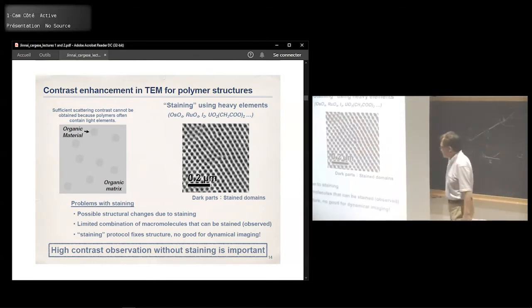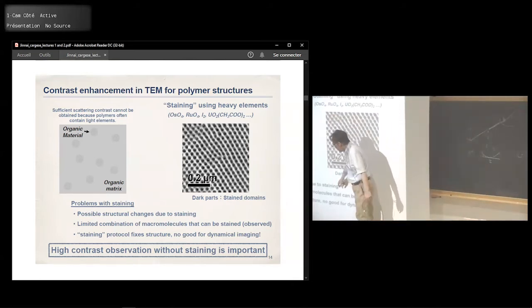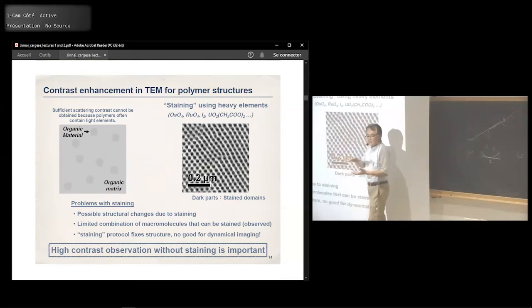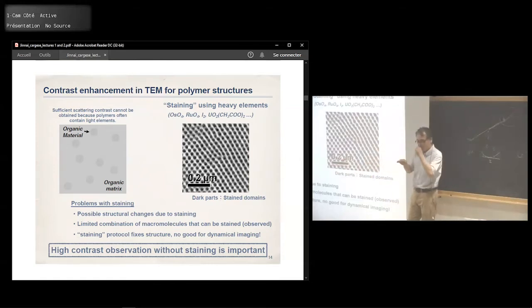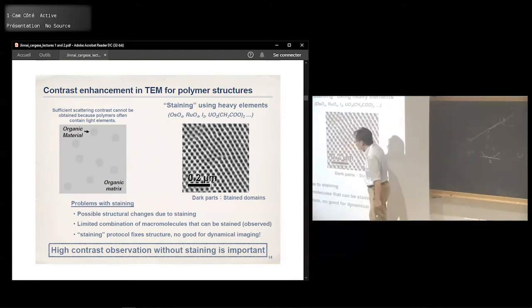You probably know that. There's a problem with this staining. When you stain, you expose the sample to the osmium tetroxide vapor, for example, and how long you expose the sample to the vapor matters. If you do that too long, then the sample will be all black. If you expose the sample for a very short time, the staining may not be sufficient, so we don't have enough contrast. So how long you expose the sample to the vapor is important. It's empirical, actually. If you do that staining in summer and in winter, it's a different thing. If you keep the sample for 5 minutes in winter and in summer, it's a different staining, okay? And the structure may change due to this staining too.